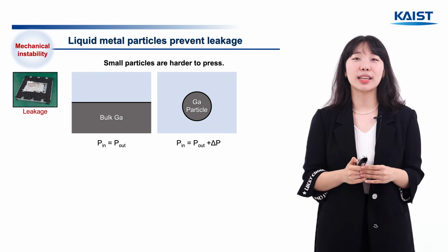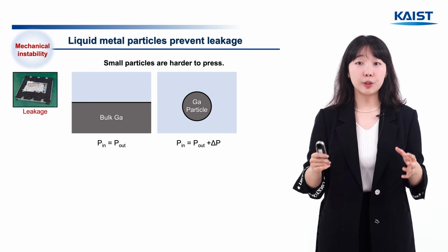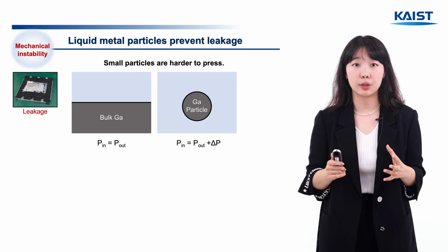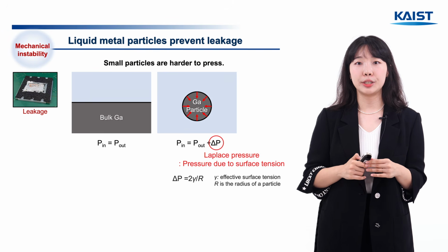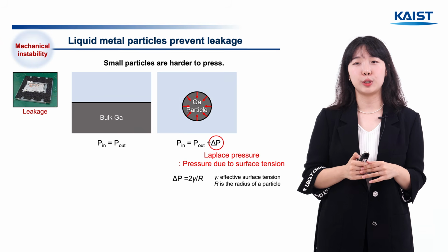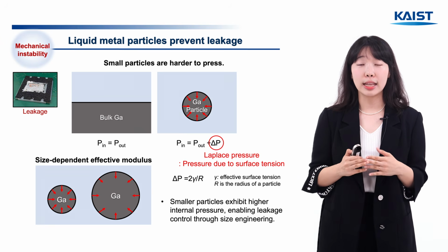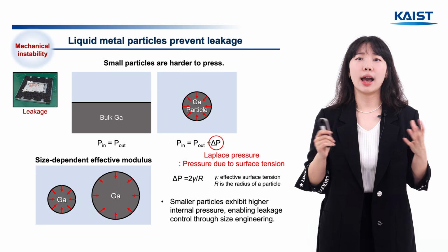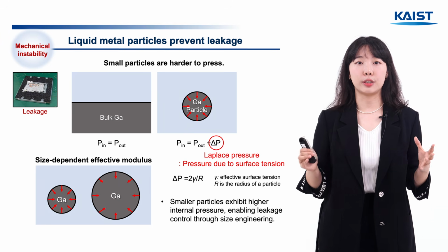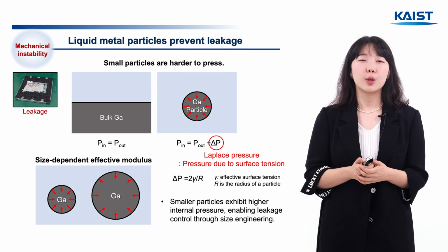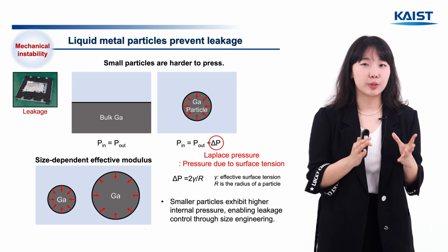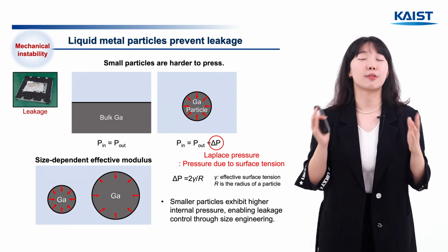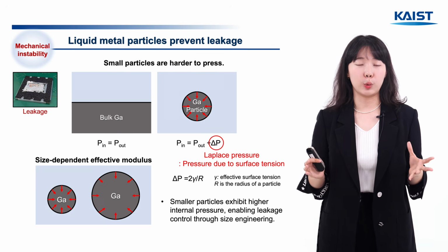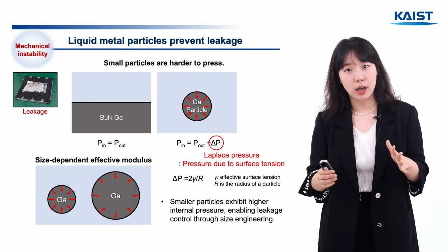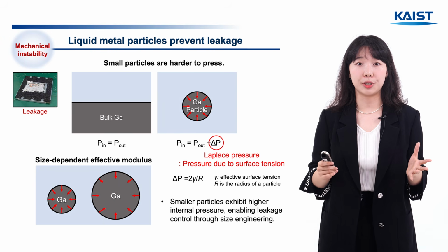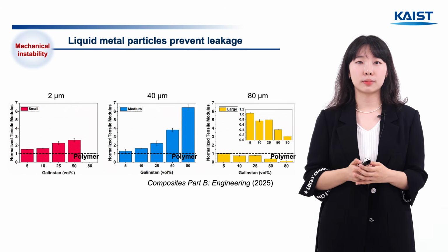First, when bulk gallium is turned into particles, surface tension raises the internal pressure. This is called Laplace pressure, and it's inversely proportional to the radius, which means that the smaller the particle, the higher the internal pressure and the higher the effective elastic modulus. You can think of high internal pressure like a balloon filled with a lot of air. Just as a balloon filled with a lot of air is hard to press, a particle with high internal pressure is also hard to press.